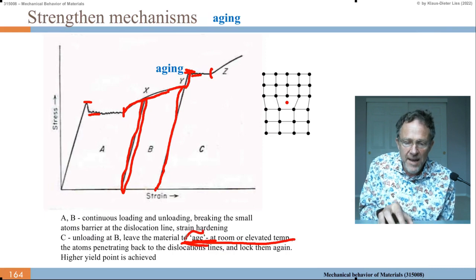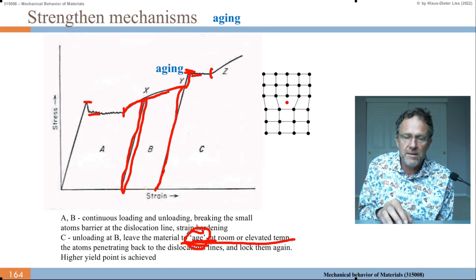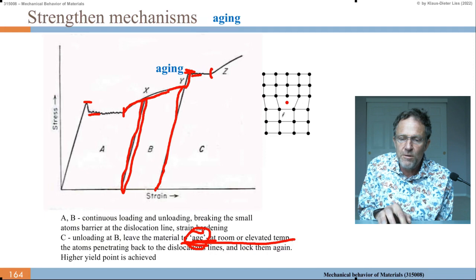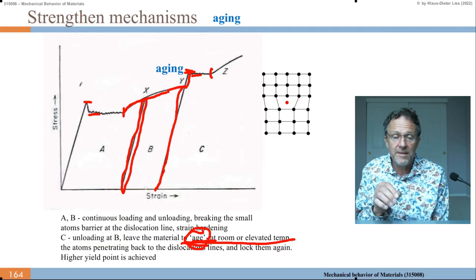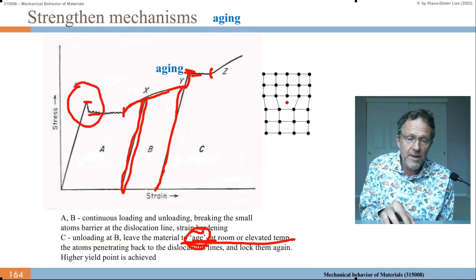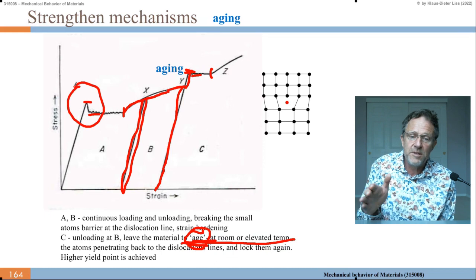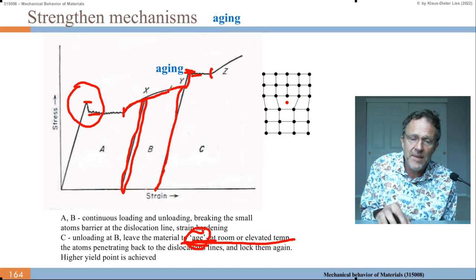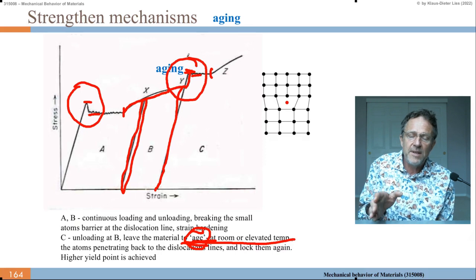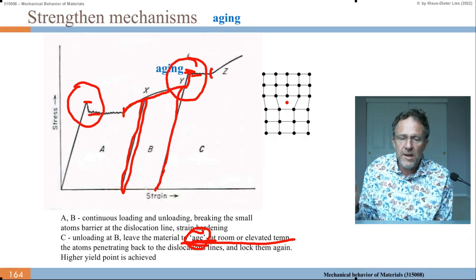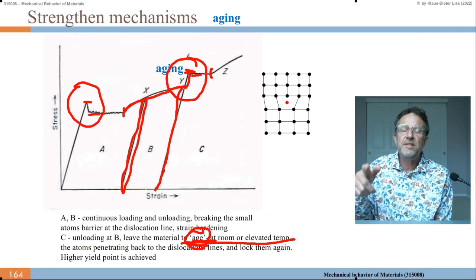But if we do aging, we make it old, we wait. If we do the aging, then the diffusion time becomes important, the carbon moves back to the new locations of the dislocations. So here were the old positions of dislocations. Then we move the dislocations. We age here. During the aging, the carbon goes to the new locations of the dislocations. And then we start with the Lüders band again.